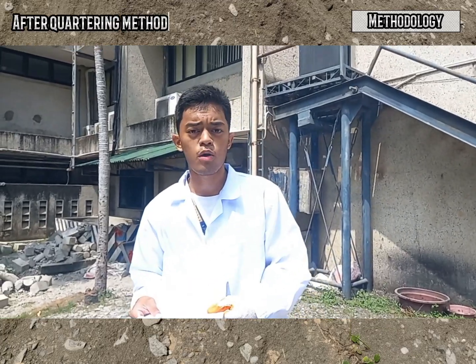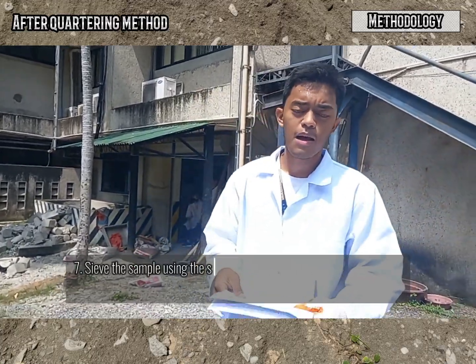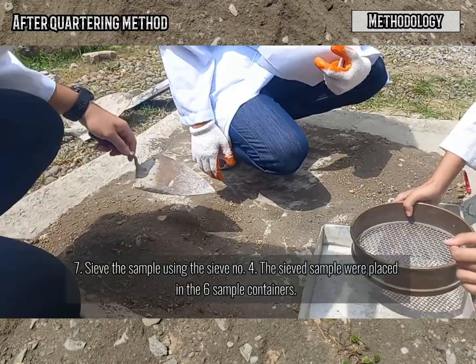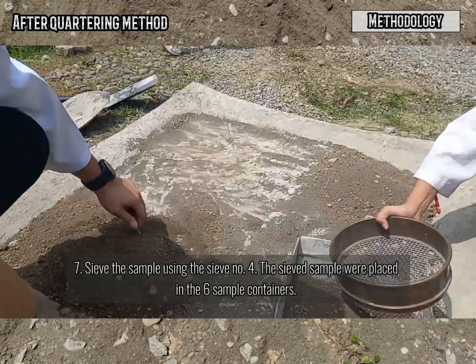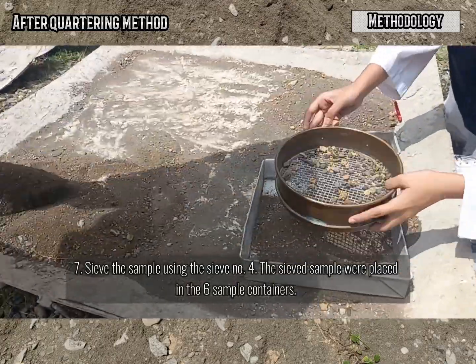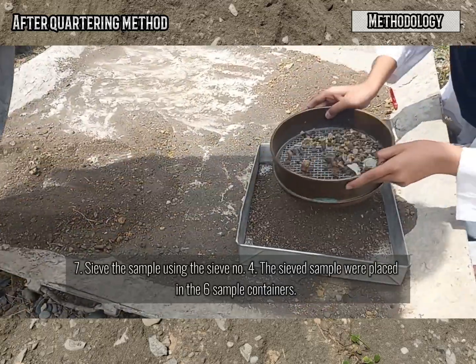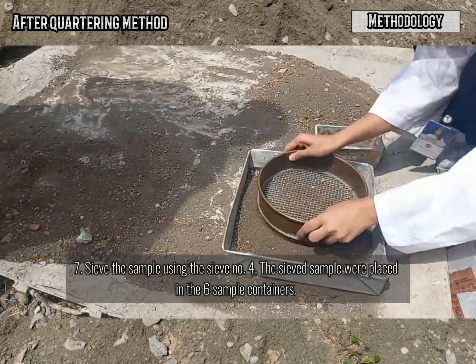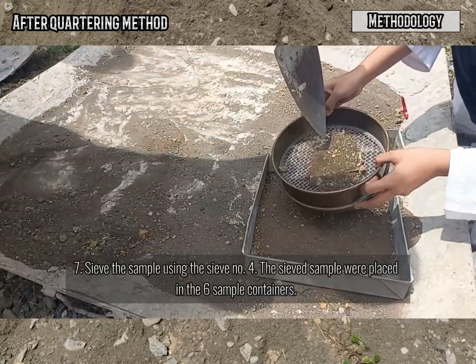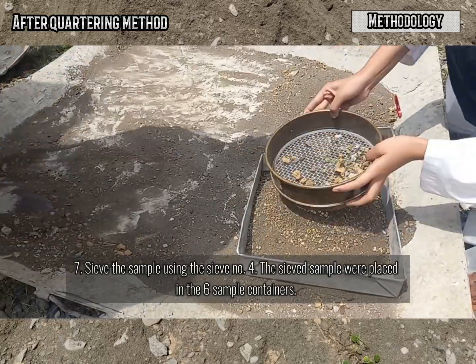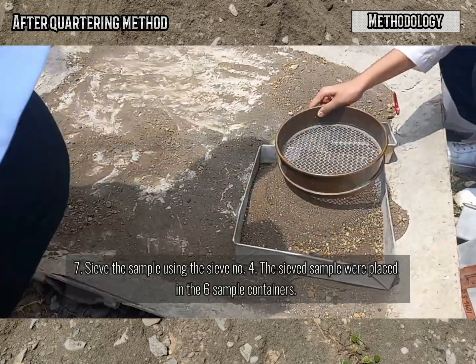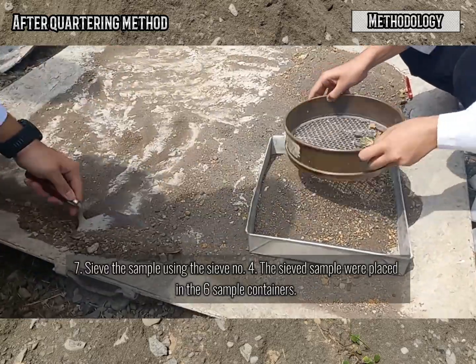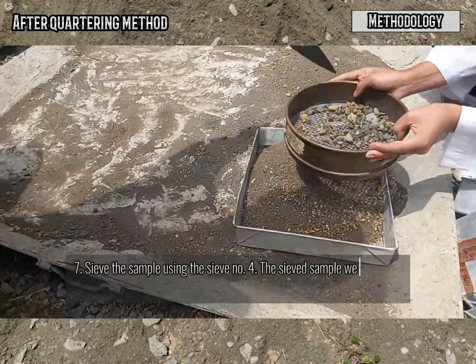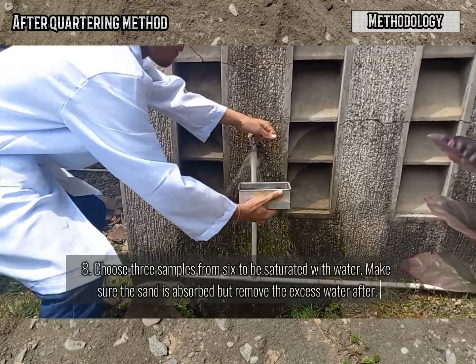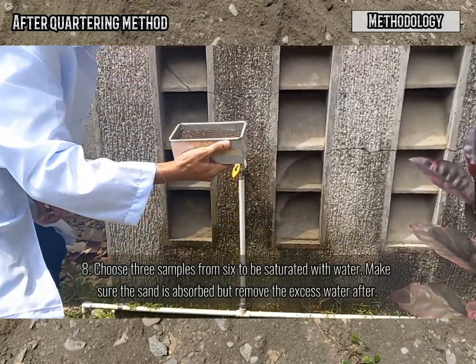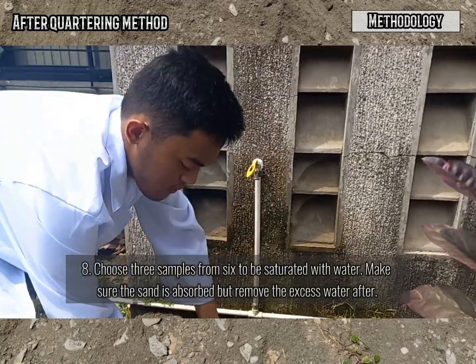So we move on to the steps after the quartering method. The first step is to sieve the sample using sieve number 4. Choose 3 samples from 6 to be saturated with water. Make sure the sand is absorbed, but remove the excess water after.